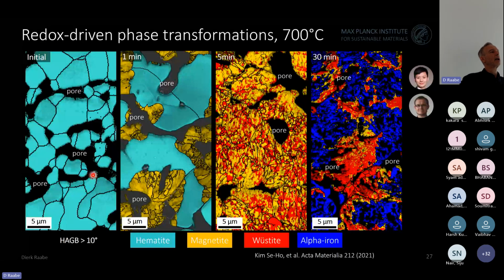And then you have the black lines indicating grain boundaries in the hematite. And then you see this nice polycrystalline structure of the initial hematite here in this blue color. Now, when we go at 700, a little bit ahead towards 1 minute reaction exposure towards pure hydrogen, again, the atmosphere is pure hydrogen, you see magnetite here in the yellow color. And that is forming more in an Avrami type of nucleation growth process.